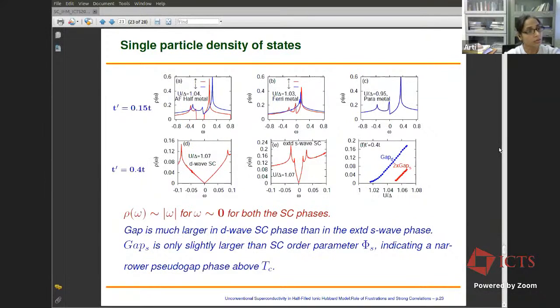And if you look at the density of states in the superconducting phase, of course in the D-wave superconducting phase, you see a linear dispersion in the density of states, which is a characterization of normal quasi-particles in this phase. But interestingly, even in the extended S-wave, we see the linear dispersion in the density of states. The linear behavior of the density of states at very small energy scale is because we have these small electron pockets, Fermi pockets, where the superconductivity takes place. And at those small pockets, even for the extended S-wave, the varying amplitude is small.